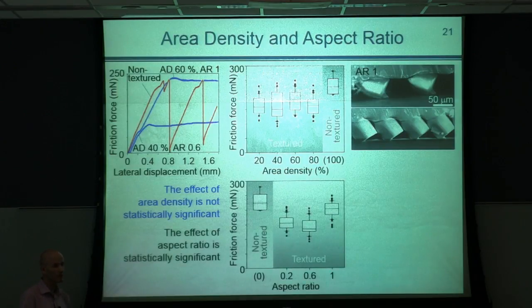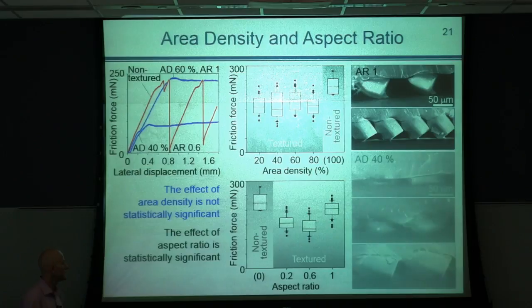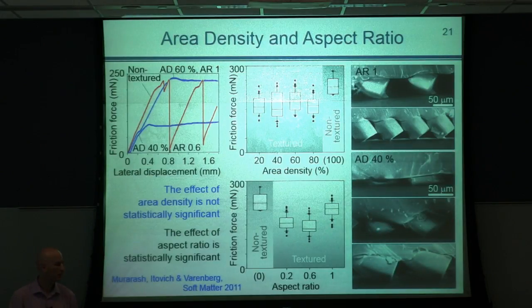When looking at the effect of aspect ratio, here we start seeing some results, and clearly some optimum can be observed. Again, it can be explained based on the geometry, on the images of different surface projections shown here. When they are low or when they are high, they are characterized by different stiffness, and when shear stress is applied, they bend to a different extent. The surfaces that are very low keep their base area in contact, while the projections that are very high bend and fall on their sides. So in both of these cases, contact area can be quite large, so measured friction will be high.